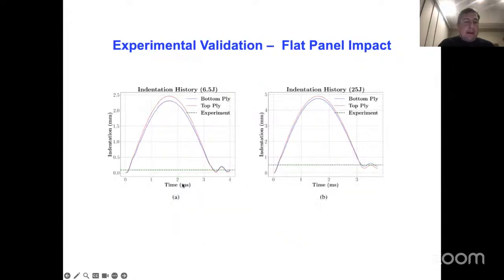Now, on this plot, I'm showing a history of the displacement. We take a point of the top ply and the bottom ply directly under the impactor, and we plot the displacement at that point as a function of time. You can see the displacement ramps up as the impactor drops down. At maximum displacement, the impactor turns around, it gets bounced off the structure. The displacement goes back to 0, but instead of going directly to 0, it oscillates around a non-zero value. And that non-zero value is exactly the size of the dent that was measured experimentally.